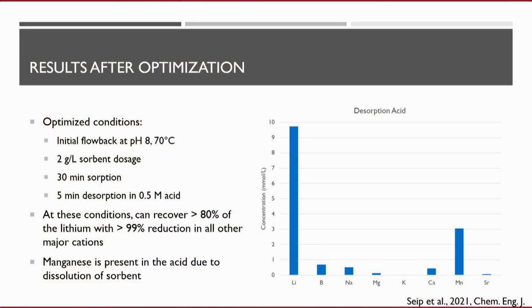This is what you get. I just want to show you a little bit of specific data. Here's that acid I was talking about. Look, it has a ton of lithium, about 10 millimolar. Look at sodium, which is a third bar over. Keeping in mind that sodium was present at a concentration 1,000 times higher than lithium when we started, now it's less than 10% of the concentration of lithium. So the selectivity factors in these are very high.